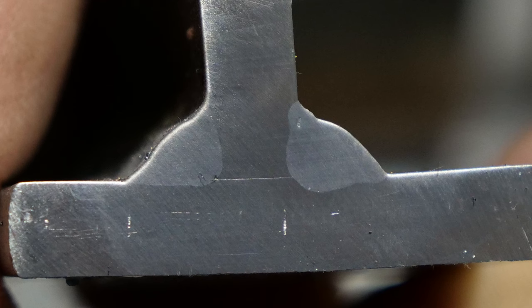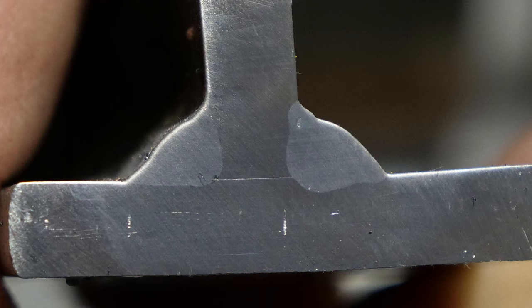From a strength perspective, there's no question that the flux core wire weld is stronger. The question is does it matter? I would say yes, depending on what you're welding. You probably need the strength of the root fusion on quarter inch plate, especially if you're doing single pass. Now there is porosity at that top right of that flux core weld, and that's typical when I've done cut and etches on flux core wire.